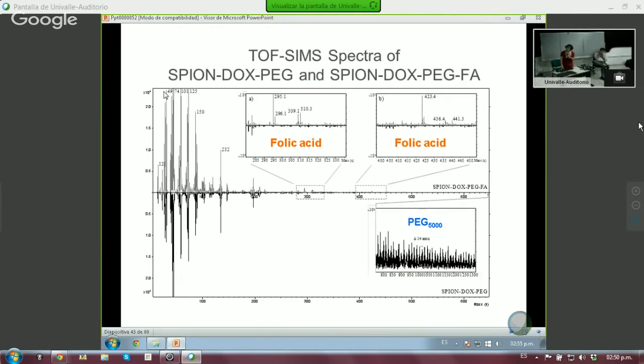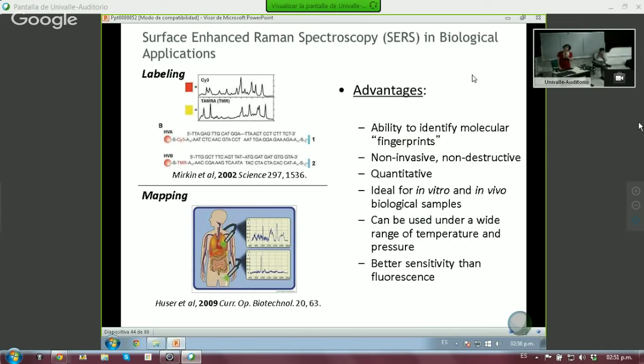And then from it, what we came up with is that the outer surface, in the case where we have the PEG, we only see the PEG. And when we have the folic acid, we see the nitrogen related to the folic acid. So anyway, these measurements convinced us that we had exactly what we aimed to have. Basically, we have these nanoparticles, and the DOX is inside. And then all that is outside is the PEG and the folic acid. So there is no danger of having the DOX being directly in contact with the tissue.